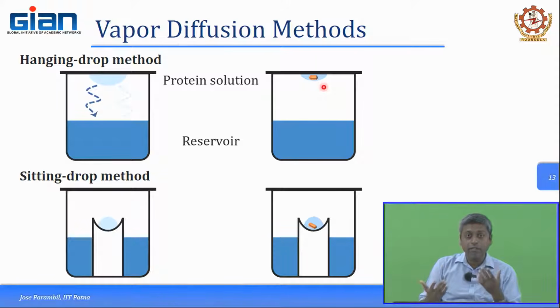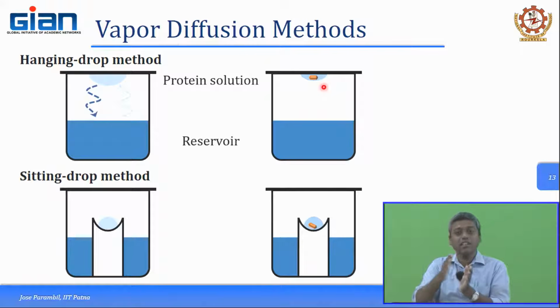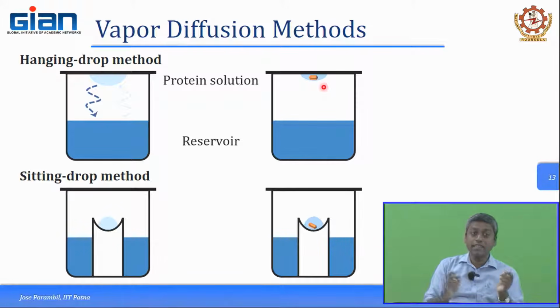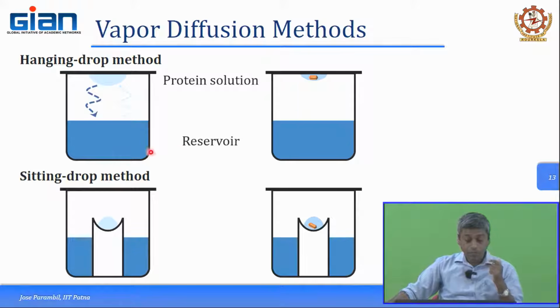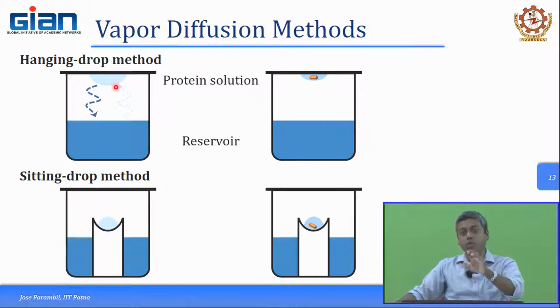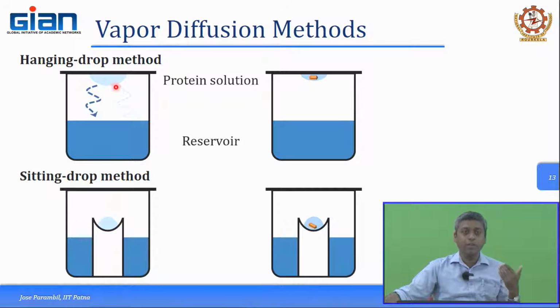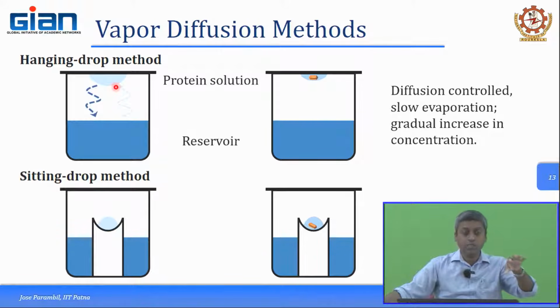But how much time do you need to give in the nucleation zone? Typically quite long, a few hours and sometimes a few days. Which means that you have to evaporate at a very low rate. That is where the diffusion becomes the controlling factor. So, by fine tuning the concentration of the materials in your reservoir as well as in the protein solution, by changing the salt concentration, the buffer concentration, or the pH itself, all of these things can change the vapor diffusion rate, and which can eventually lead to a nice region that would hold the materials for quite a long time in the nucleation zone in order to ensure proper nucleation of the protein. So, that is one of the conventional and most reliable protocols often used for screening a number of diffusions and various conditions for protein crystallization.